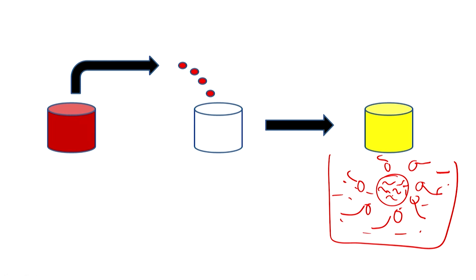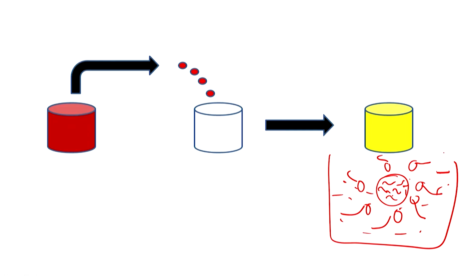Now, if I heat this dispersion beyond the boiling temperature of the chloroform, but less than the boiling temperature of the water, what will happen? The chloroform will slowly leave the system, leaving the polymer chain in the aqueous system, decorated in a micellar structure by the surfactant.